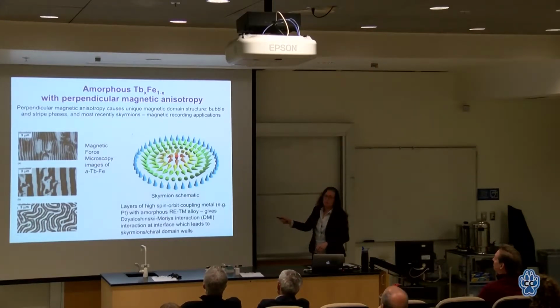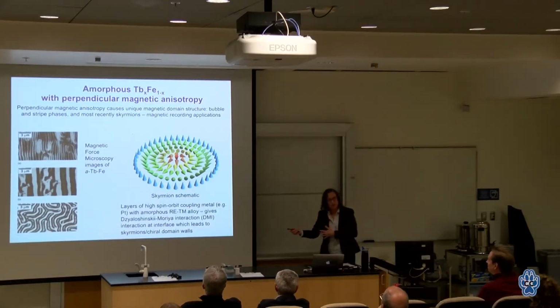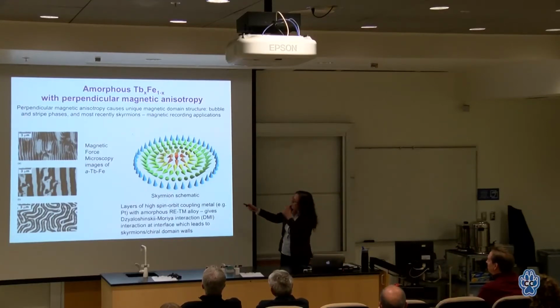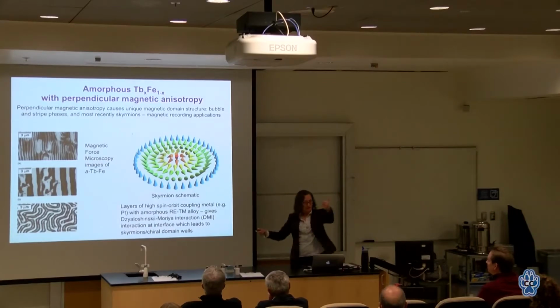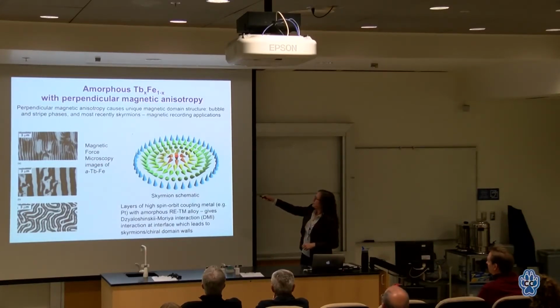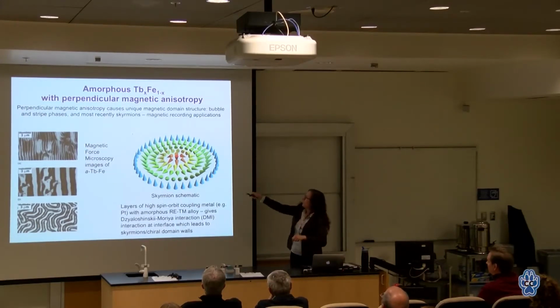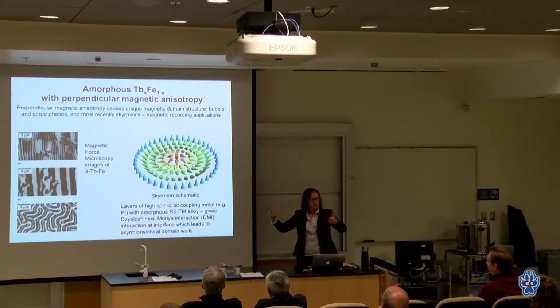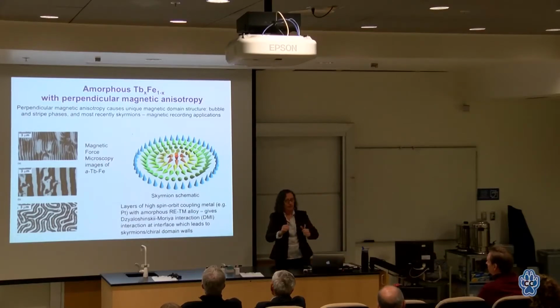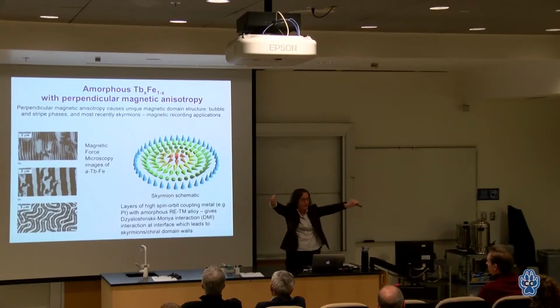More recently, people have been very hot on the topic of skyrmions. And what skyrmions are, I've shown them schematically here. Because it's magnetized out of the plane, by the way, in and out are equal, it can't care which. Imagine that the center of this bubble-like thing, I have it pointing down, and then all the way out here, it's pointing up. So that's like a domain. But it does it with a particular chirality. And so in this image, the chirality is out. It starts down, and then it goes out like that.